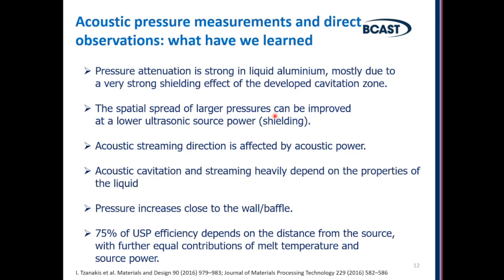We know now how this shielding and also attenuation happens in real liquid melts, and we know that the acoustic streaming, so these secondary flows, acoustic flows, are affected by acoustic power. We can also draw a lot of practical solutions which we can apply in our practical applications of liquid metal processing from these measurements.